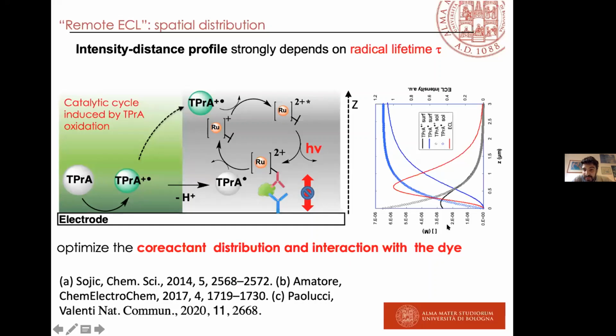Here I take a very nice plot from a Sojic paper. So you can see here, this is the electrode surface, this is the concentration of the radical. Sorry, this is the distance from the electrode surface towards the bulk of the solution. You see the red signal is the ECL emission. You see we have a maximum around 0.5 to 1 micrometer distance from the electrode surface, and after that a decay. This maximum depends on the radical lifetime.